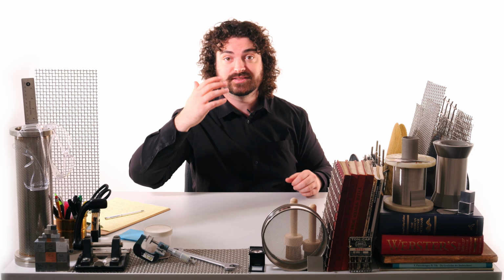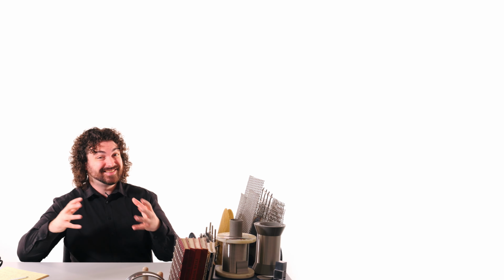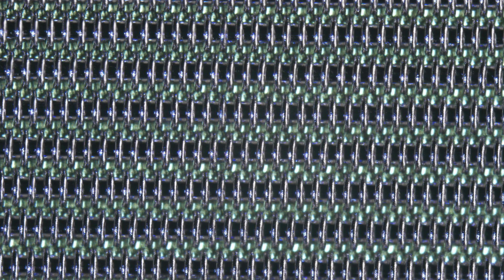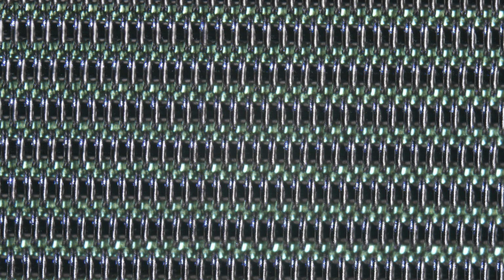Advanced applications like metallurgical refining, gasification, and pre-SCR polishing push filtration systems into that 650 to 1000 degrees Celsius range, 1200 to 1832 Fahrenheit. At these extremes, even minor exposure to ambient air could cause rapid cooling, leading to cracking, condensation of aggressive compounds, and catastrophic media failure. Ceramic filters made from low-density refractory fibers and alloys are preferred for their thermal shock resistance and cleanability. Woven wire mesh is also great to combat thermal shock. These systems often incorporate heat tracing and predictive monitoring to maintain safe conditions.